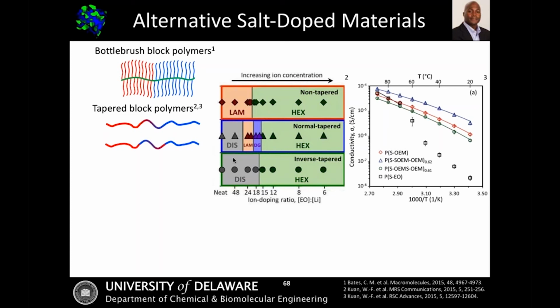Now, if I move to the inverse taper, which is basically just an opposite or different type of taper, I can see that disordered region lasts longer. I won't go too much into the reasons why, but the key thing to think about is that we're actually decreasing the segregation strength or improving the processability of these materials. Not only are we able to improve the processability and tune the morphology by using the tapers, we can also do things to actually tune the conductivity.